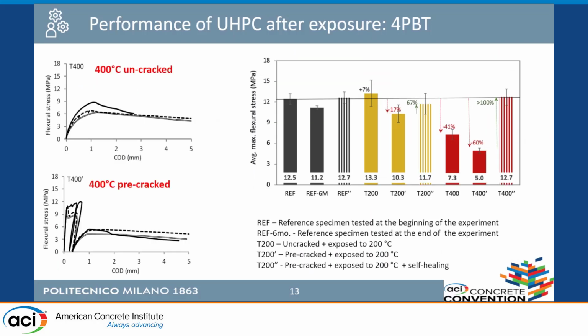So here, trying to sum up, on the left, the gray rectangle refers to reference concrete. So you see that we have some scattering, while the yellow one represents the results after heating. So you can see that if we do not perform any pre-cracking, we don't have damage, okay? So practically we have the same value of flexural strength as before heating.